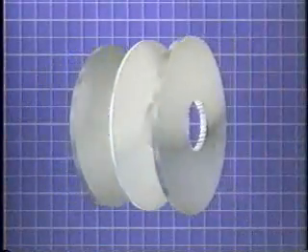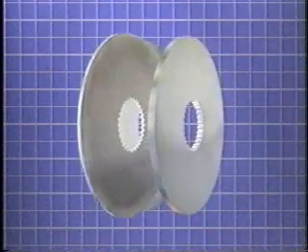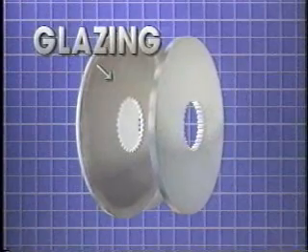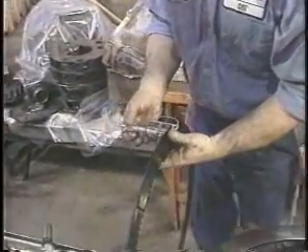Friction materials are porous. As they're squeezed during engagement, oil oozes through the material to the surface, where it dissipates heat and prevents wear. Through a process not yet completely understood, oxidative byproducts from the oil can form a glaze on the friction material. This reduces the material's porosity and restricts the flow of oil. With less oil flow, there's more heat, more oxidation, more glazing. The problem quickly compounds itself until the clutch fails. All of these thermal degradation factors combine to reduce clutch life.